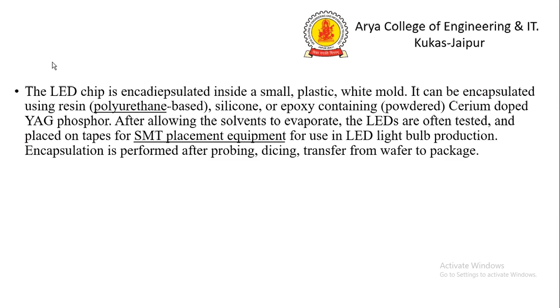The LED chip is encapsulated inside a small plastic white mold. It can be encapsulated using resin, polyurethane based silicone, or epoxy containing powdered cerium doped YAG phosphor.